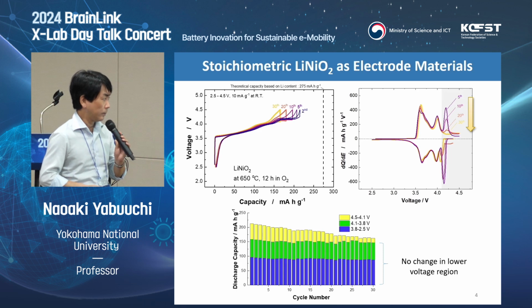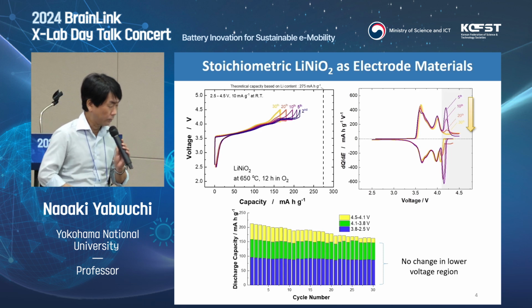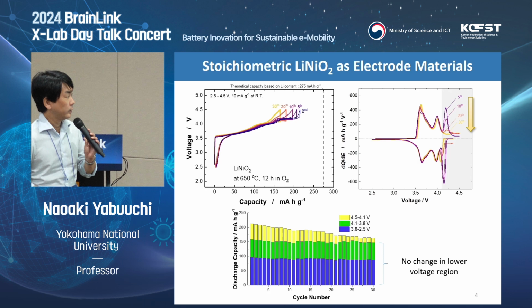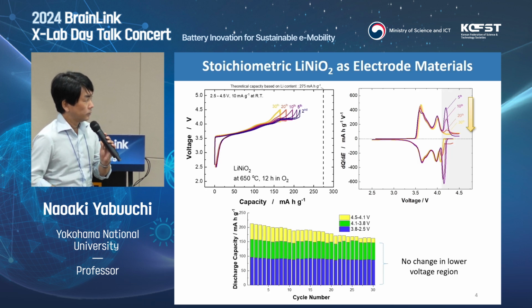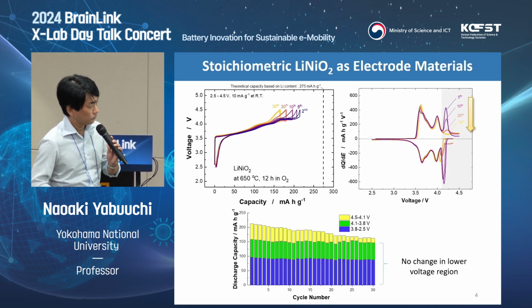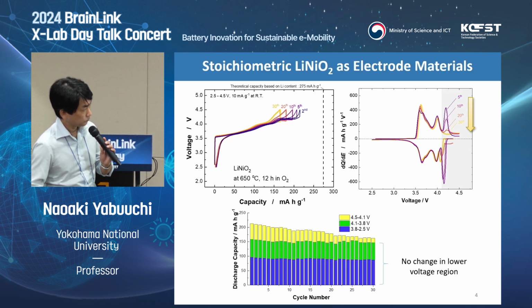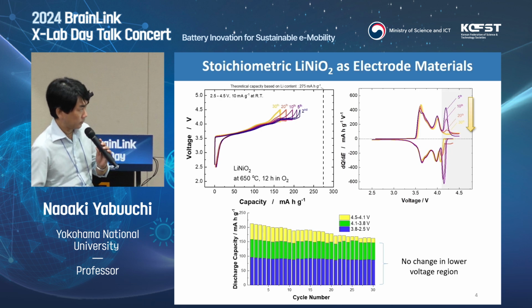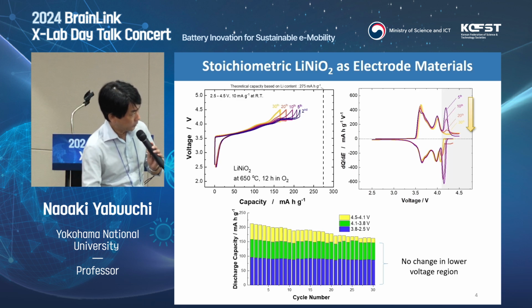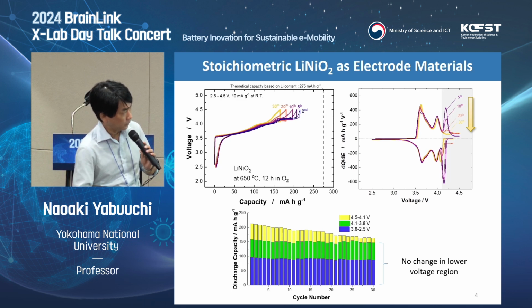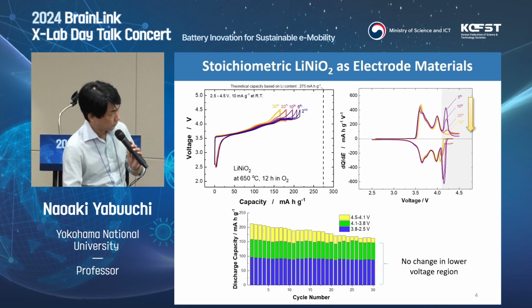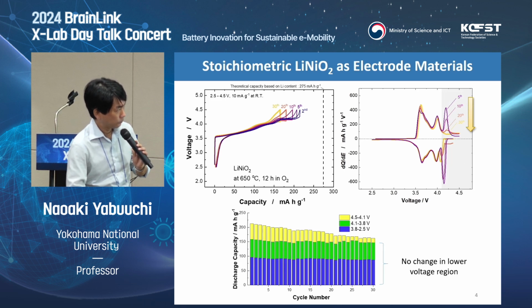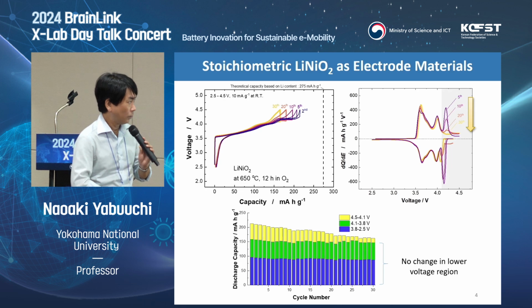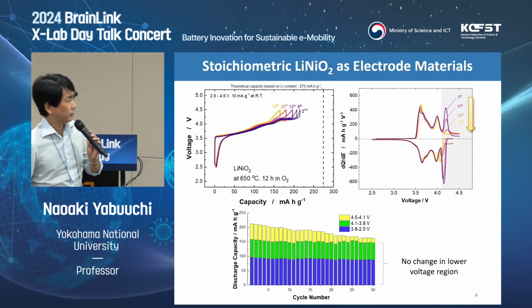The initial discharge capacity is very high, over 200 milliampere hours per gram. However, you can see clear degradation upon cycling. When you look at the differential capacity plot here, a very unique degradation process is observed. Only in the high voltage region, the so-called H2, H3 phase, H3 to H4 phase transition region, is degradation observed. In the lower voltage region, you cannot see any changes at a low rate. So this is a very unique degradation process.